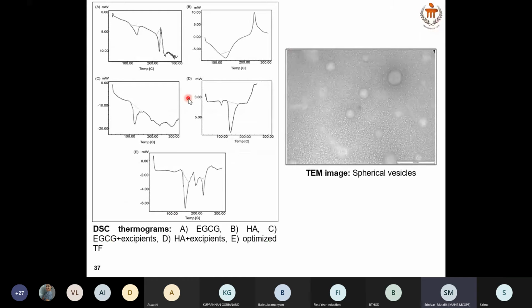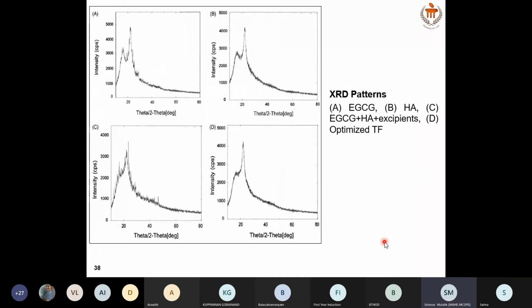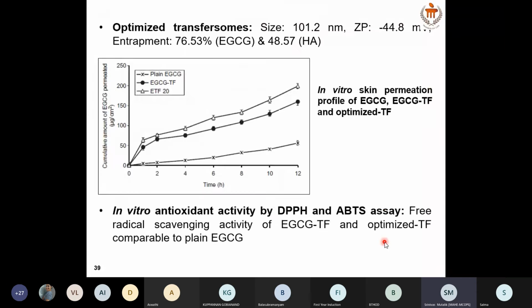So these are some of the tests which we performed, and the spherical vesicles were observed in transmission electron microscopy in the size range of less than 200 nanometers. Then we conducted XRD, X-ray diffraction studies, where we observed that the drug is present in the amorphous form. Then optimized transferosomes, the size was around 100 nanometers, zeta potential was negative, entrapment efficiency was around 75% for EGCG and 50% for hyaluronic acid.